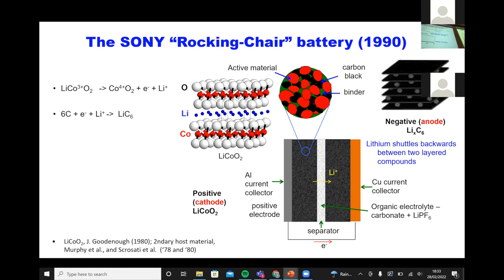You can vary both the redox couple and the structure to try to get different voltages. Lithium in carbon has a potential versus lithium metal that's almost the same — the fully lithiated LiC6 has a half-cell couple of about 70 millivolts, so it's almost as reduced as lithium itself. Lithium cobalt oxide sits between about 3.6 and 4.3 volts if you pull out about 50% of the lithium. A phosphate like lithium cobalt phosphate can push the voltage even further.